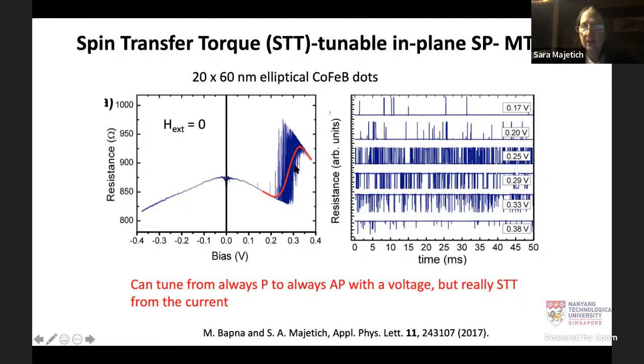And if you look at this as a function of voltage and sit at particular bias voltages, then you see that at 0.17 volts, it is spending most of its time in the low resistance state, occasionally going to high resistance. If you go to 0.38 volts, it's mostly in the high resistance state and occasionally dropping down. But again, in this particular device, 20 by 60 nanometers, we were getting sort of millisecond time response. And so we wanted to get faster than that.